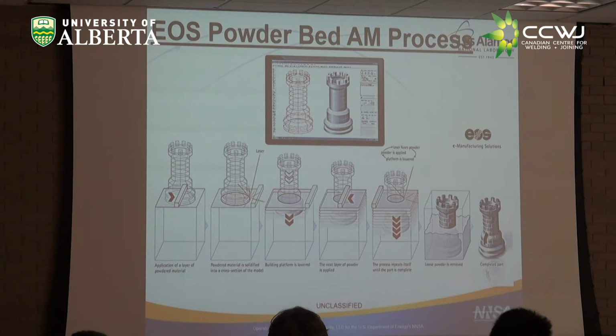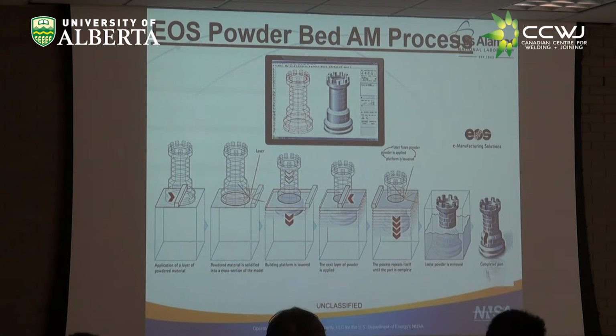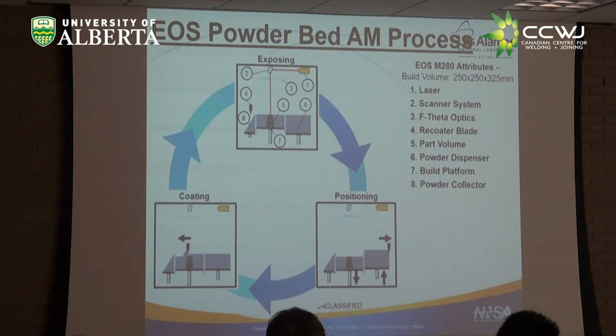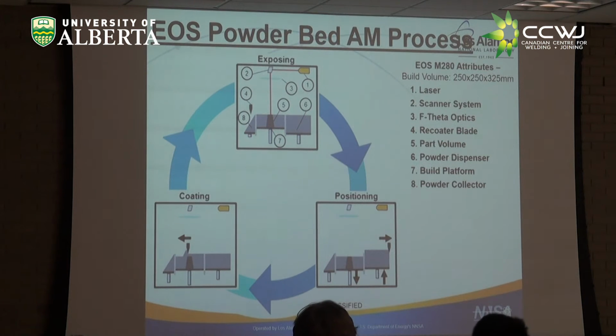The way this works is sort of shown here. There's a thin layer of powder taken from a supply and spread in a very thin layer across the build plate by a wiper, which is usually ceramic or metal, and the beam then rasters over the part in a pre-programmed way, and then the middle box is let down by 40 microns and another layer of powder spread over it. And this continues until you build the whole part up, and then it's buried in all this powder, and you take the powder away and you have this, in this case, this chess piece here. And you do this over and over and over again by a layered process.